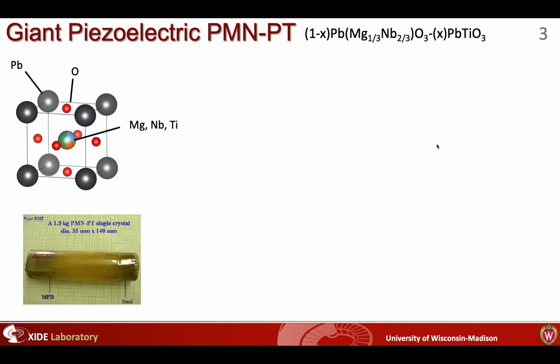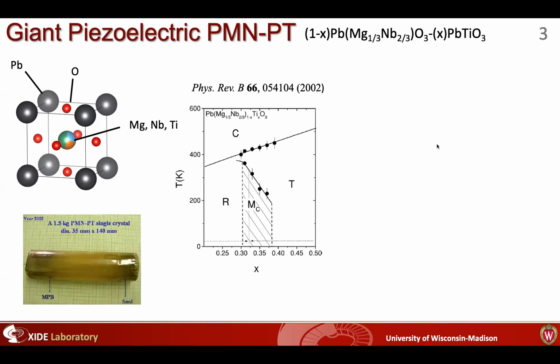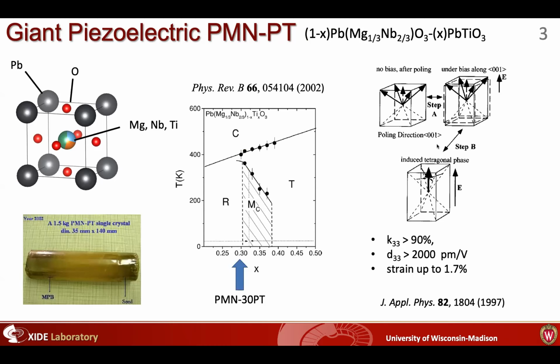Our material of choice was the giant piezoelectric lead magnesium niobate-lead titanate. As Lane Martin highlighted, it's a solid solution of PMN-PT. If you choose a composition near a morphotropic phase boundary, you get a flattening of free energy profiles that give competing rhombohedral and tetragonal symmetries. So when you apply an electric field, you can have a field-induced phase transition from rhombohedral to tetragonal. And that's where you get these giant electromechanical coupling coefficients and giant piezoelectricity.